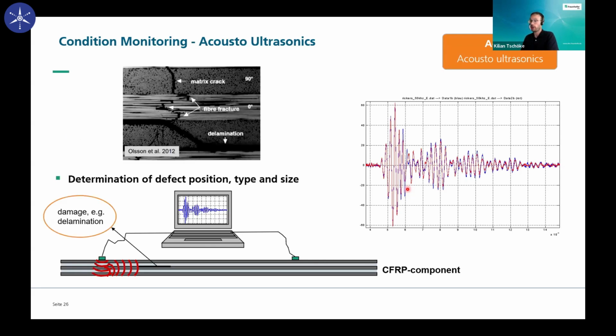Especially for carbon fiber or glass fiber, this is a really useful tool because you can monitor for non-visible damage. I think you know that in composites and carbon fiber, damage can be under the surface where you cannot see the impact, for example, but can be really, really dangerous. And these waves, as you've seen, they propagate into the full cross-section of your structure, and can be used to monitor damage not visible from the outside, from the surface, in really complex structures. I want to start with an easy example